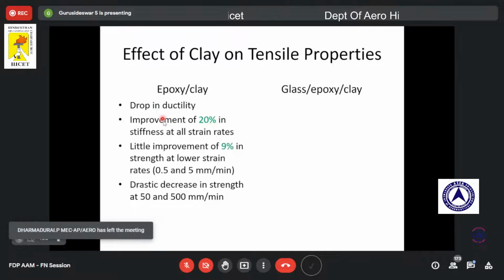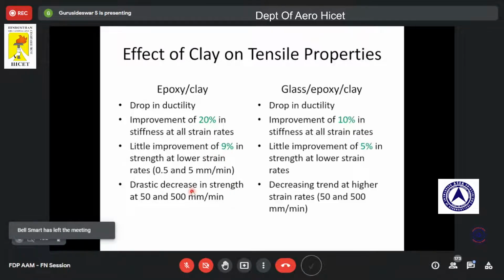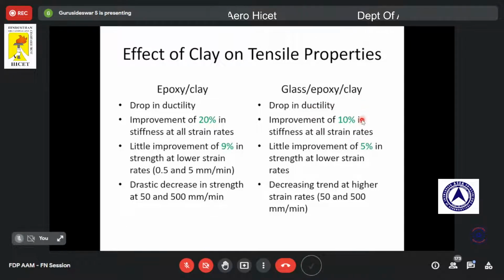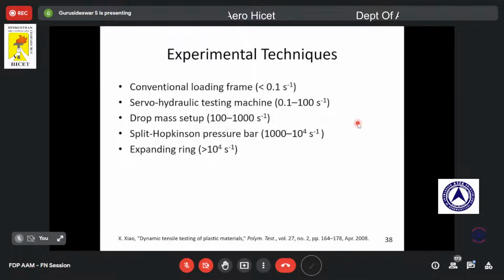As I told earlier, there is a drop in ductility, there is improvement in stiffness, there is improvement in strength, and again these are the results which we got for glass epoxy clay composites. So our observation is that epoxy, glass epoxy, epoxy clay and glass epoxy clay composites are all rate sensitive. This is what we observed from this study. Now, so far we have focused on low strain rate. By using UTM, I can have different crosshead speeds, I can do different strain rates. Now, how can I achieve higher strain rate?